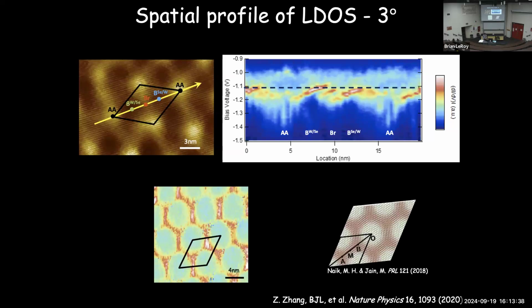If I take a two-dimensional image of it, this is what this state looks like. I'm taking this image just at this particular energy here. And what I see is that the electrons are all living on the edge of these hexagons. So they're living along certain stacking configurations in the sample. These are calculations of what the expected density of states looks like in this structure, which matches fairly well if you look at the unit cell of how the electrons are sitting.